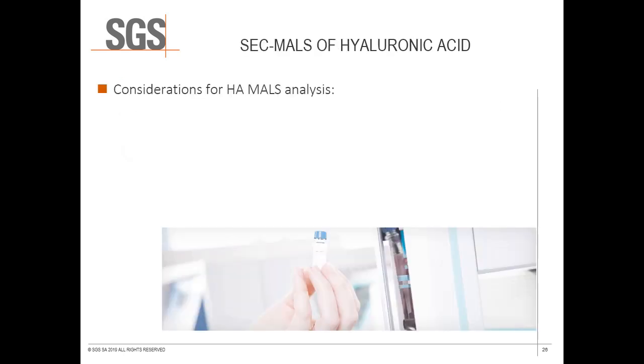With its high molar mass and viscosity, certain considerations must be made for molar mass analysis. First, because of the large molecule size and weak chain bonding strength, hyaluronic acid samples are susceptible to shear degradation, not only during sample preparation, but also during analysis. Though sample filtration is a normal part of molar mass analysis in order to prevent small particles from creating noisy light scattering responses, it is not recommended that polymers over 1 million grams per mole be filtered. Low-speed centrifugation for 30 minutes will typically remove insoluble particles to an adequate degree.